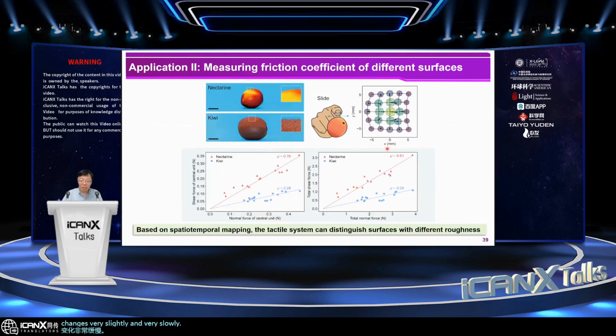Okay. In addition to modulus measurements, the tactile system can be also used to measure the frictional coefficient between the skin and other target objects. According to the difference of the frictional coefficient, the 3D skin can potentially distinguish a rough surface from a smooth surface. So this slide shows the testing results of the 3D skin sliding on the surface of the nectarine and the kiwi surface. And you can see clear difference in the frictional coefficient.